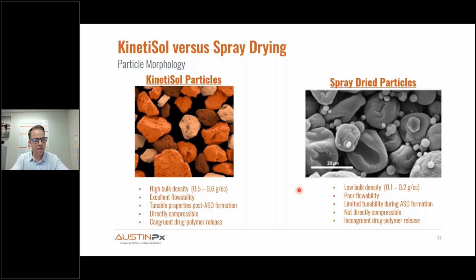And so they're very different. If you look at the SEMs of the two particles, it's very different. Kinetisol particles are very dense, sort of granular. Spray-dried particles, as we all know, are sort of hollow spheres, corrugated spheres. So what does this mean in terms of downstream handling? Well, for one, kinetisol material coming out of the milling process has very high bulk density, typically 0.5, 0.6. Contrast that to spray drying, as many of you know. Spray-dried powder has very low bulk density, and therefore it has to be densified in order to be further processed into a final dosage form. Our kinetisol material has excellent flowability, whereas bulk spray-dried powder tends to not flow well.